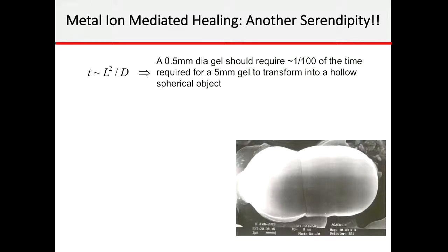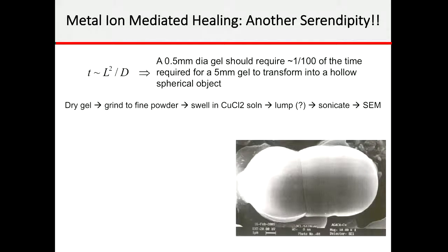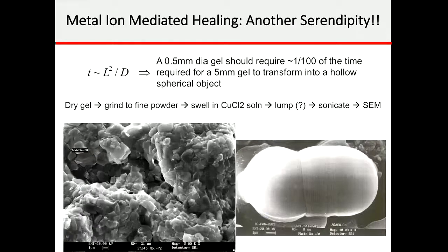We said that 1/100th of the time will be taken if we had small size, and basically we'll take the dry gel, grind it to fine powder, and swell it in copper chloride solution, but we always get a lump. The particles are always sticking together, and this is a scanning electron microscope study. So this was a failed experiment, so to say. That means we recognize this as a failed experiment.